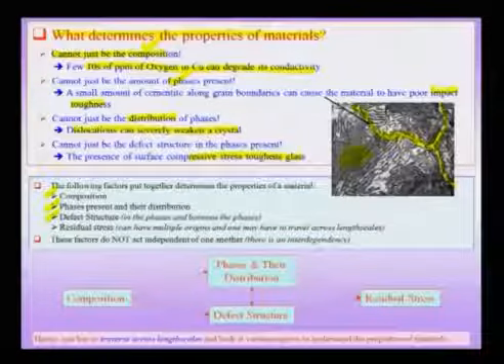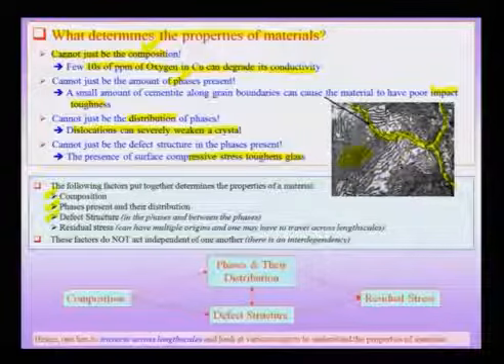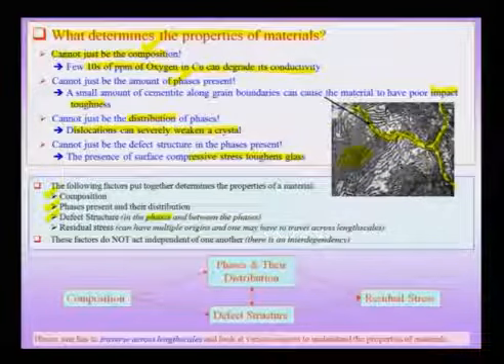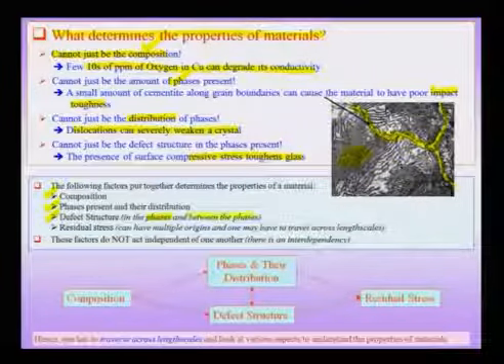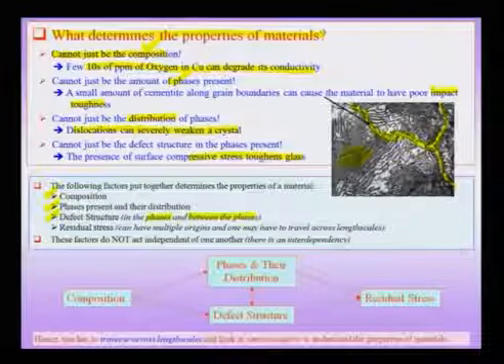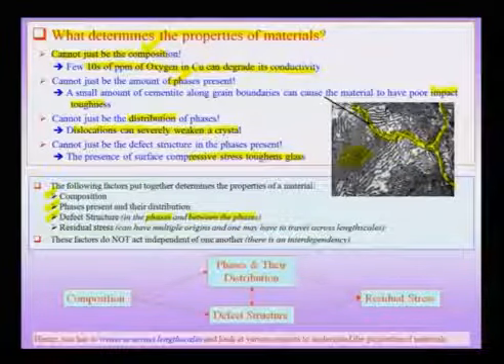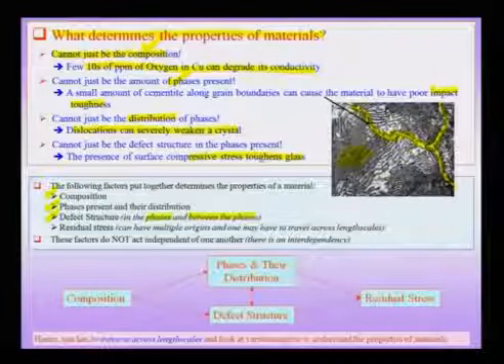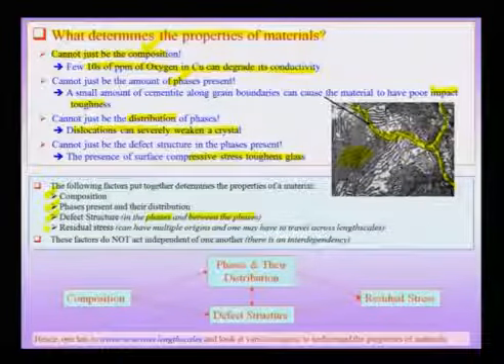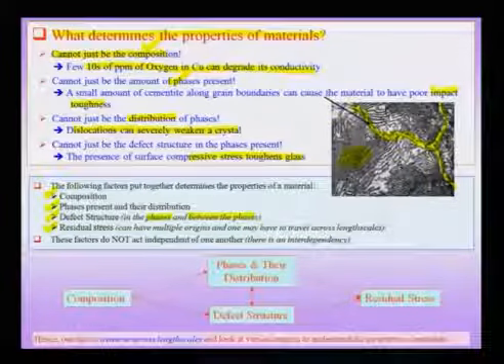So, when you are talking about defect structures, I am talking about defects present in the phases, like dislocations in the phase, and between the phases, like for instance interfacial dislocations, apart from the bulk dislocations. Last but not the least, I need to know the residual stress, and as we shall see later, residual stress can have multiple origins. To understand all these aspects, I not only need to know the phases present and their distribution, I need to know the defect structure and its distribution, I also need to know my residual stress and its distribution.